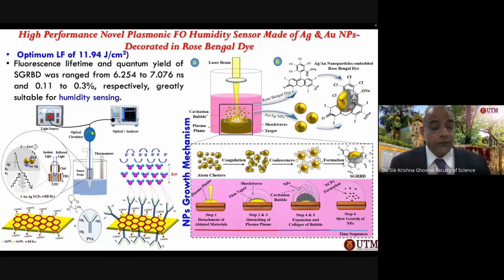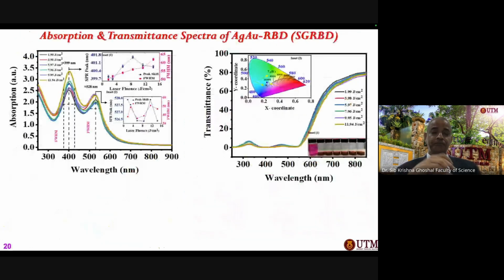But before we go through the sensing, we also put a PVA layer, polyvinyl alcohol layer, to enhance the probability of attachment of these molecules. And we have found that the layer of PVA molecule works very nicely, and we can really use them for the high performance detection system.